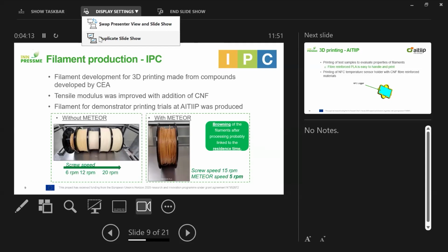It was PLA with 10% of CNF, and this was then produced as a compound to be then reworked to filaments at IPC, where different testing was made with different compounding machines and extrusion machines to evaluate the influence of these processes on the material properties. And it can be seen that the mechanical properties, especially the tensile modulus, was improved with the addition of the CNF fibers.